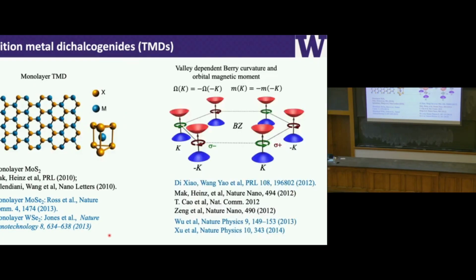The broken inversion symmetry leads to what we call valley contrasting properties. Here I show you the momentum space of this monolayer TMD. We have these six corners of the Brillouin zone. It's a semiconductor, so we have a band gap at the corners of the Brillouin zone. What's important is that for individual valleys, such as K and minus K, we have a non-vanishing valley moment, and the result is distinct optical selection rules. So the K valley couples to sigma plus polarized light, and the minus K valley couples to sigma minus polarized light.